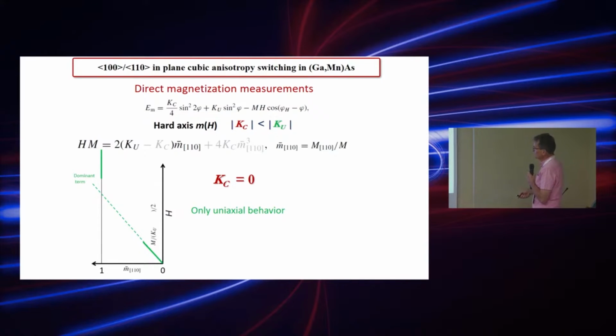So the magnetization should go this way, because this is a linear relationship between H and M. So M is here, H is over there. So it's a linear increase. Of course, mathematics says it should go infinitely, but the physics says M cannot be greater than 1. So we should get something like that. How exactly it goes is not particularly important. There is a very important factor here: the slope is set by the value of the uniaxial anisotropy. So this is just M over Ku divided by 2.